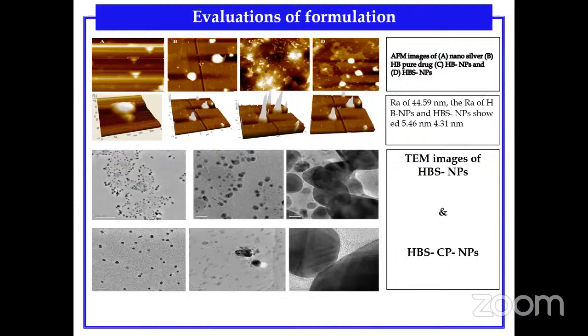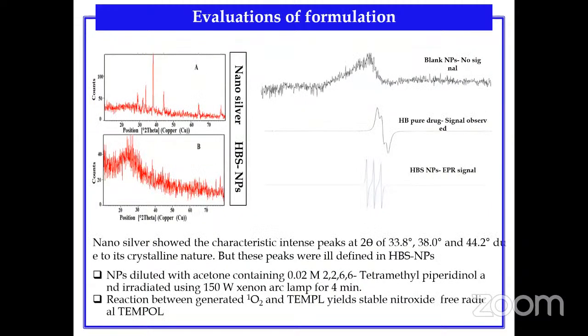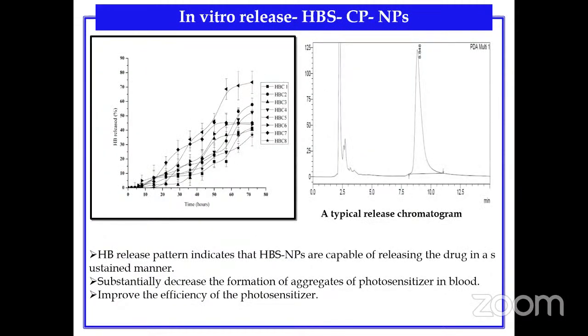Again, we have evaluated by AFM for the roughness of the systems. The roughness of the system is important to show enhanced surface plasmon effect. When that light is passed, we are using silver. That silver will undergo or produce a surface plasmon effect, due to which we'll be able to see more amount of drug release. So that light conversion will be better. Similarly, we have done the other characterizations for that silver and that system.